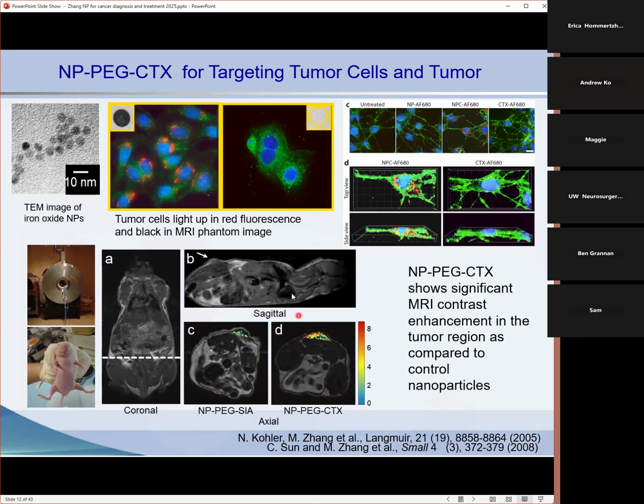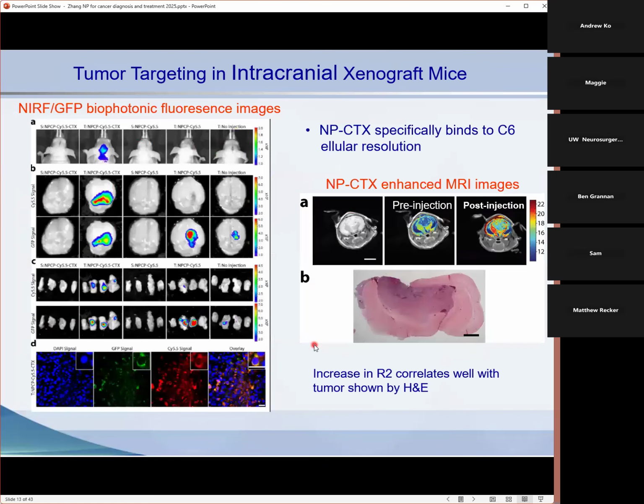We also injected control nanoparticles, nanoparticle-PEG, and nanoparticle-PEG-chlorotoxin into a xenograft mouse model. And here's a tumor. We can see that compared to the control nanoparticles, the nanoparticle-PEG-chlorotoxin targeted nanoparticle mainly shows in the tumor region in this model. We also demonstrate our nanoparticle targeting intracranial xenograft mice.